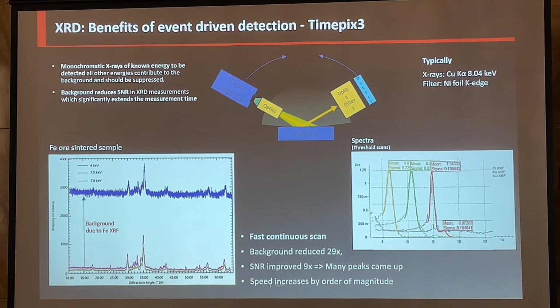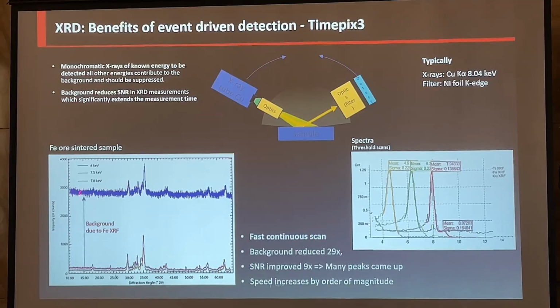But unfortunately, very often you don't have only the XRD reflected beam, but you also have some scattered radiation coming out of the surface. There could also be fluorescence coming from the sample. That's pretty often. And this background, unfortunately, also carries some noise. So your peaks are, of course, seen on top of this noise. And to be able to separate them, you need to have high statistics.